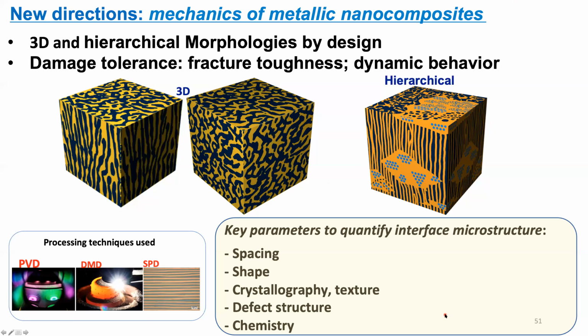Hi, Professor. I really love the talk. I just wanted to ask you, in the hierarchical and in the random structure, how do you measure the K1C? Because the K1C you showed is sigma y pertaining to a particular metal. So if you don't know how the structure is changing, I mean when it's moving from one material to the other, how do you measure the K1C or the strain energy release rate overall of the material?